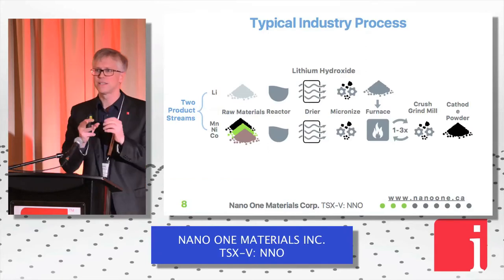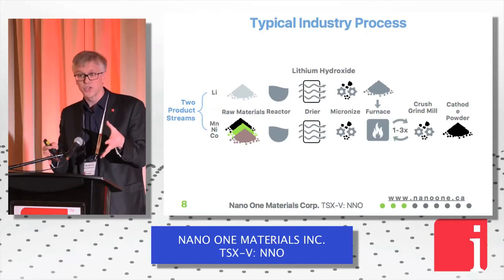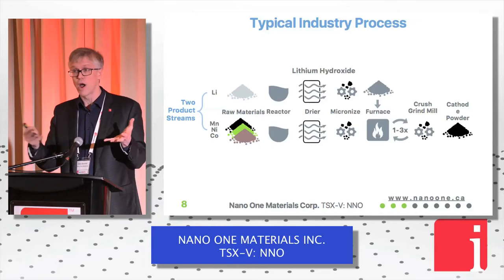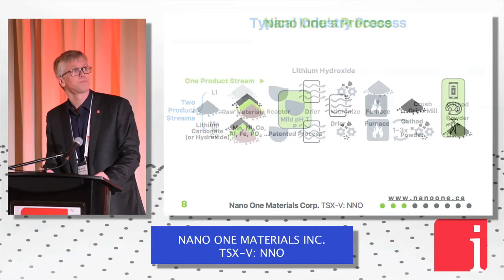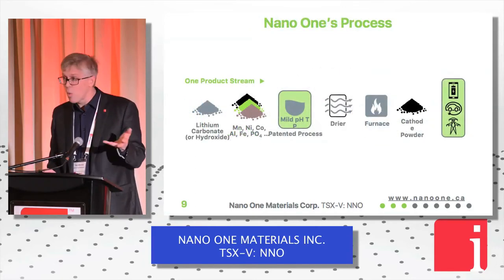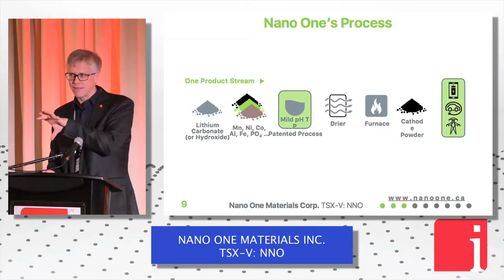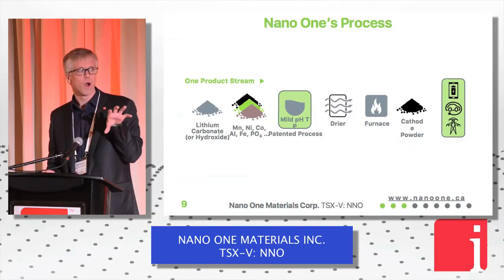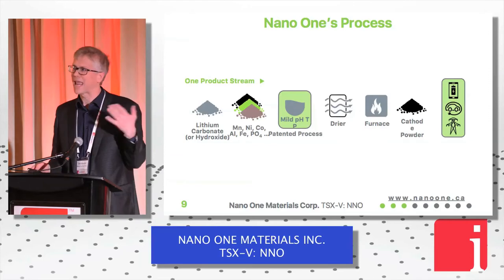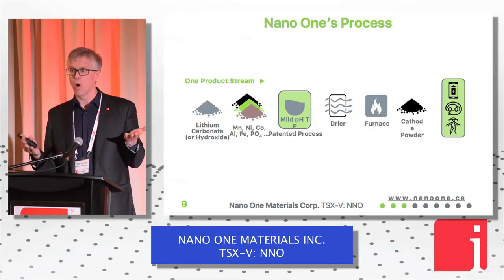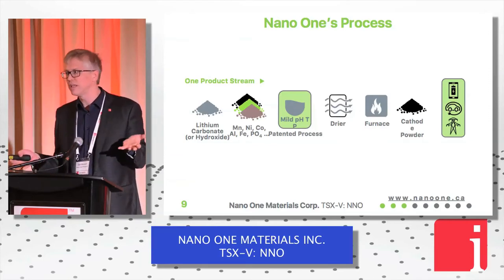Everything melts and coalesces together until you get these structures that are able to store lithium ions during the charge and discharge cycle. In Nano One's process, we actually amalgamate these two streams into one. So we have one product stream. And instead of doing it mechanically, we do it chemically. We do it in water in an aqueous process, relatively low pH.